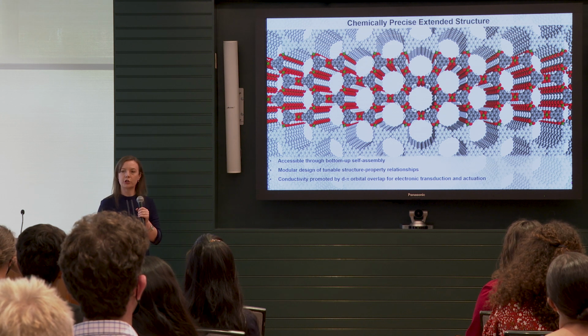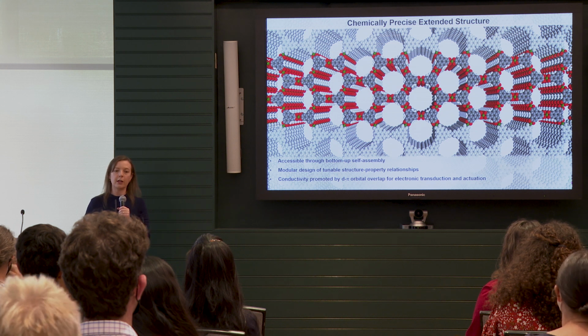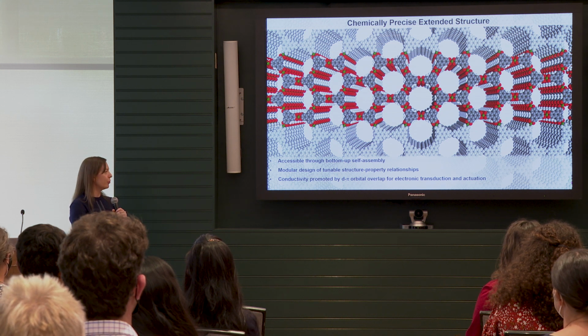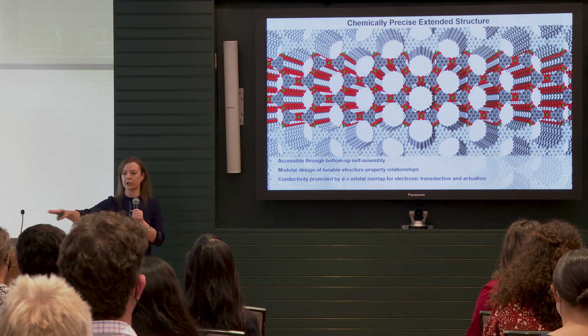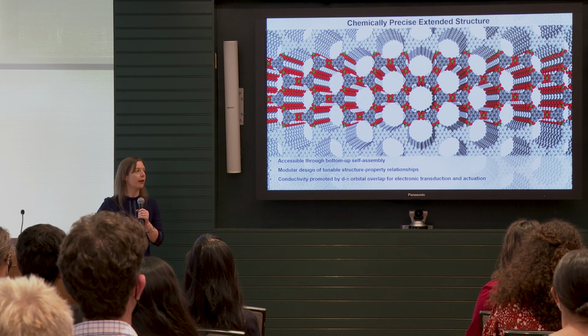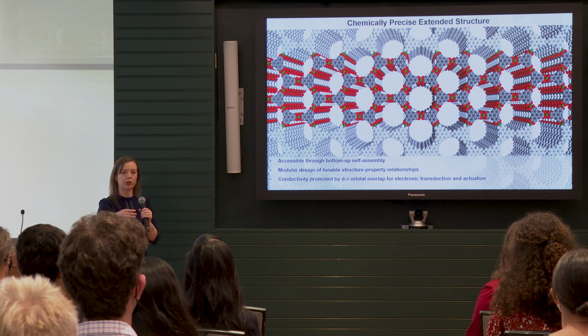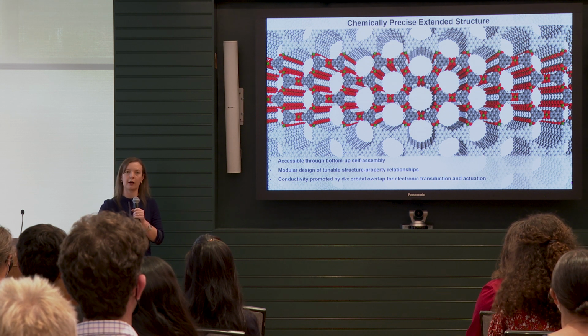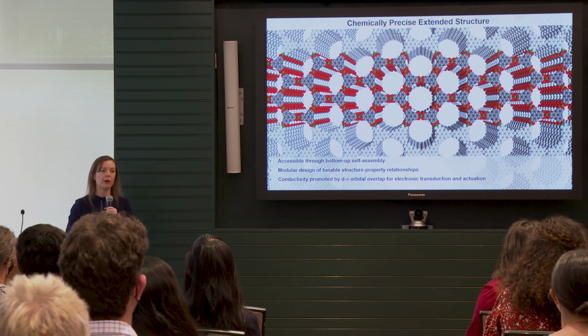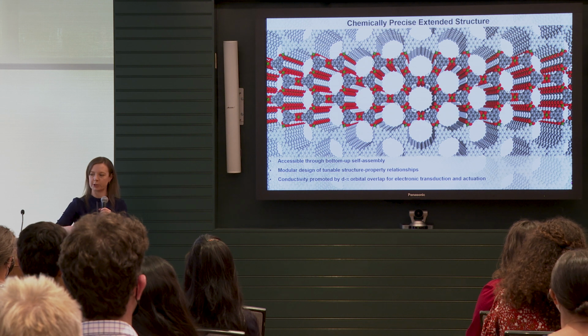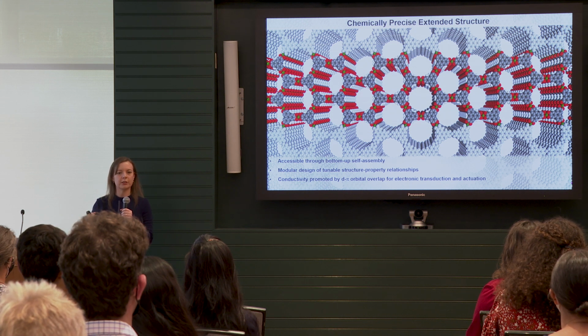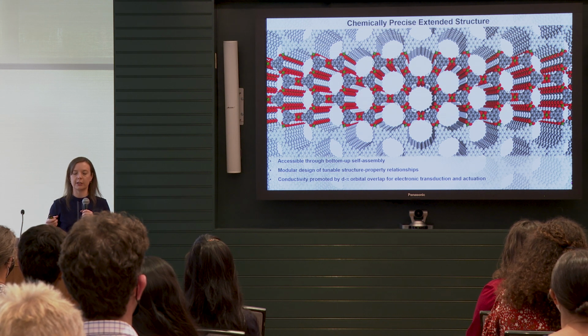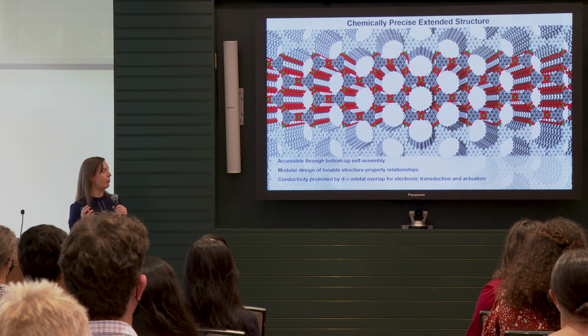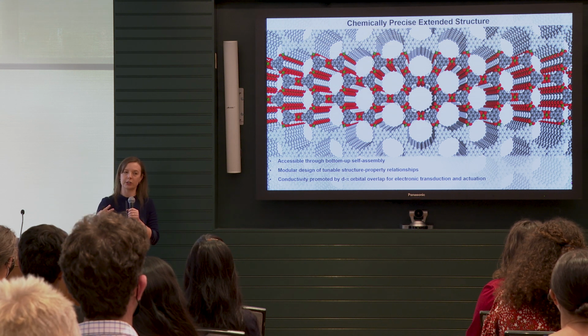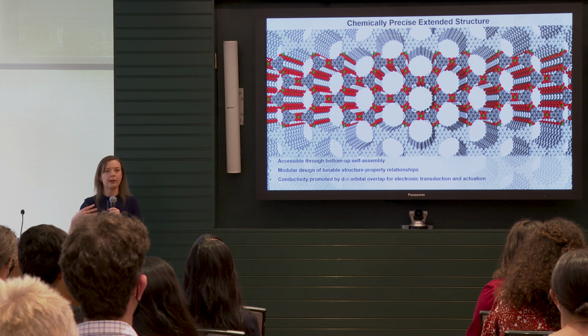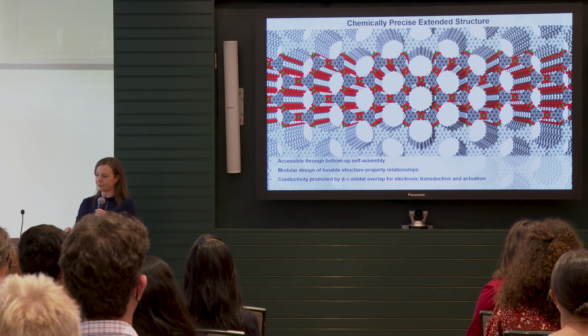And also, we have intrinsic conductivity embedded within this material through in-plane conjugation, or delocalization of electrons through the plane of the material, and in the stacked structure, a layered structure that tends to stack upon itself with multiple layers, we also can achieve conductivity through the stack. So all of those are important features for electronic signal transduction, such that if something binds to the surface of that material, it will change its conductivity and we'll be able to detect it in a portable device.